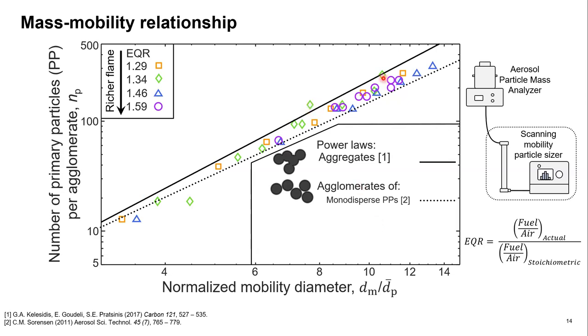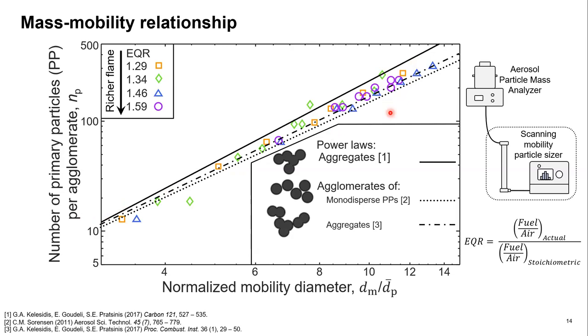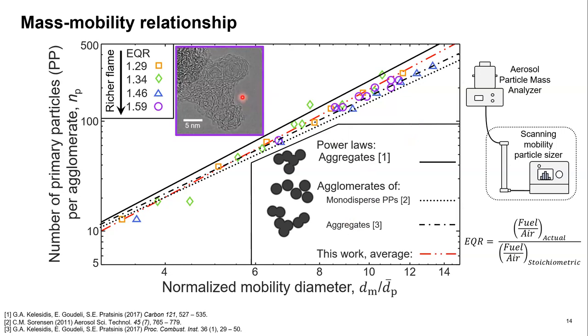What we see here is that the aggregates form an upper bound of our data, and the agglomerates form approximately a lower bound. Both of these theories converge at the small number of primary particles per agglomerate, giving approximately the same answer, and only at these larger sizes do they diverge and tell us something meaningful about our particles. What can also happen is we can have agglomerates of aggregates, so smaller aggregates joined together with weak bonds into a larger agglomerate, and this falls somewhere in the middle of these two lines. When we look at the line representing the average of all of our data, this falls close to the agglomerates of aggregates line, slightly closer to the power law for aggregates, suggesting that we have highly aggregated structures. Indeed, this is confirmed by the microscopy images, where we see evidence of significant necking between the primary particles, suggesting that they are indeed aggregated.